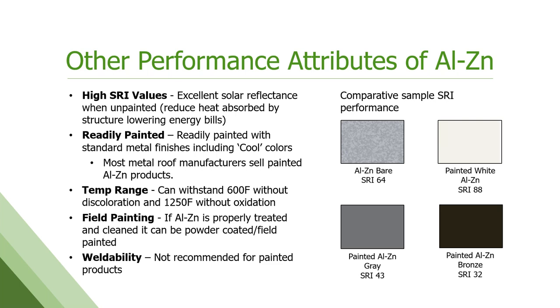This product has some really good other attributes as well. It's got high solar reflectance, SRI values, so it's great for cool roof applications and energy. Energy Star is being sunsetted for roofing, but it is on the Energy Star list. It's readily paintable and looks fantastic when it's painted. It can withstand about 600 degrees Fahrenheit consistently without discoloration, and up to 1250 degrees Fahrenheit without oxidation, so it can be used in places where high heat is a concern. The bare product can be field painted as well and powder coated if that's desired. If someone doesn't want it pre-painted, they can paint it post-installation. It can be welded except for painted products, which is the case for galvanized as well because welding will destroy the painted surface, but bare can be welded. And then we've got some examples. Bare Galvalume SRI is usually around 64 on average.